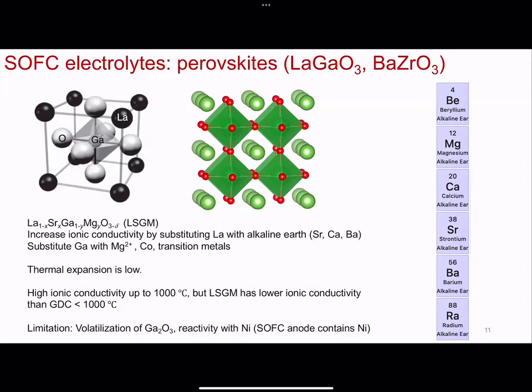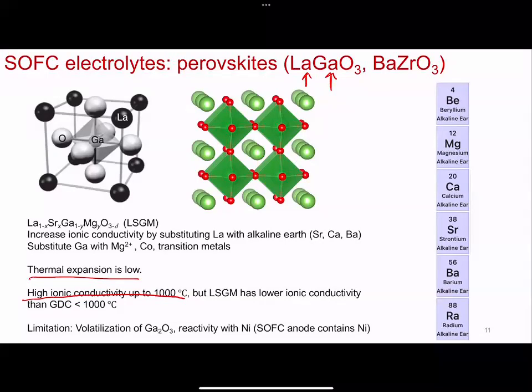I mean, you have such tunability, right? It's a ternary compound. You have tunability of the A site. You have tunability of what's called the B site, although not to be confused with boron, that's also B. So these compounds that contain lanthanum gallium oxide, barium zirconium oxide, or barium zirconate, they're also really promising solid electrolytes for SOFCs. They have high ionic conductivity. You can see here low thermal expansion, which is ideal because when you increase the temperature of your cell, if your electrolyte has too much thermal expansion, right, cracks are going to start inducing, and you're going to propagate these cracks the more you run your fuel cells, and then eventually your fuel cell will just short because it doesn't separate the cathode from the anode anymore.